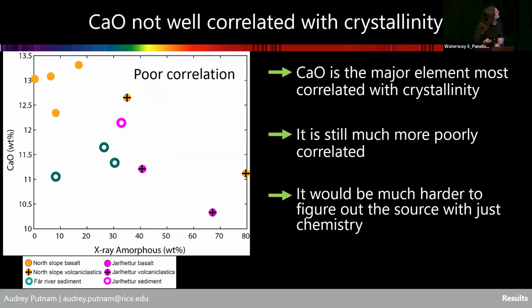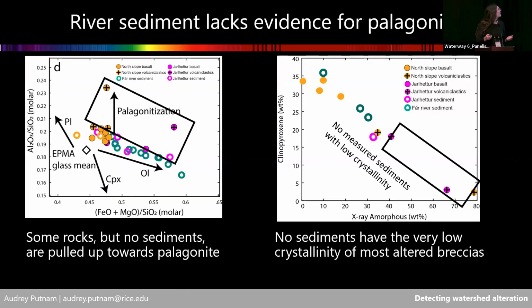And then when we look at the bulk chemistry, there are some trends, but they're not that great. This is the best correlation with X-ray amorphous content of any of the major oxides, and it would be a lot harder to try to figure out all the details that are going on here. So just trying to figure this out with bulk chemistry would be a lot more difficult. And that makes sense because these are the same compositions of lavas that are coming up and quenching in different environments. We also don't see evidence for that watershed hydrothermal alteration being expressed in these coarse-grained river sediments.